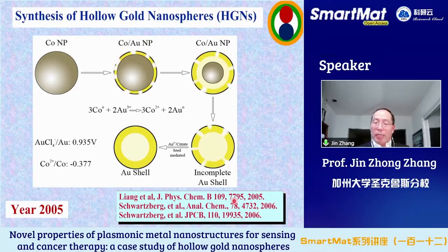After the paper was published in JPC, my grad student, Adam Schwarzberg, one of my best students in 30 years, saw the paper in JPC. He said, aha, Jim, maybe we can use this way to make the hollow gold nanospheres. Okay, to make a long story short, it took him 6 months to reproduce what Professor Wan's lab did. And in addition to what the paper did, we also added a step, added more gold salt and citrate as a way to make a better shell by blocking some of the pores you sometimes still have at the end of the reaction, okay? Let me show you.